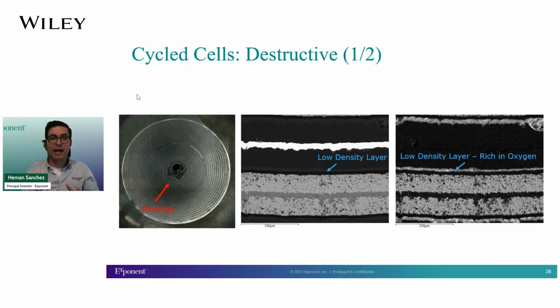So going back to that example I was showing before, why you do the cross sections and look at the quality assessment of this, because then you look at a cycled cell and you can do a side-by-side comparison, and all of a sudden you identify that you now find a low density layer that is rich in oxygen that is happening right on the surface of the negative, like right next to the separator. So that was something that we were able to identify doing a comparison before and after, combining cross-section CT, cross-sectioning, and SEM EDS mapping. So very powerful.